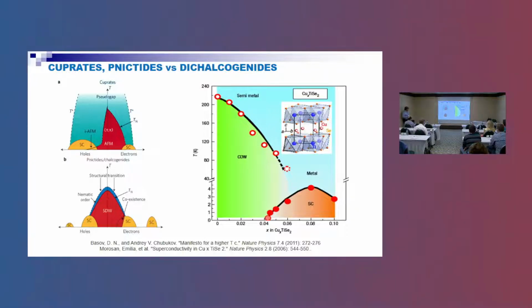Basically, after 30 years of knowing these compounds, people decided to intercalate these materials and see what happens. What is the similarity in all these cuprates and iron-based superconductors? The parent compounds are magnetic. Then if we dope or apply pressure, this magnetism goes away and we have room for superconductivity. Exactly the same we have for the charge density wave, which appears in titanium diselenide. If we intercalate with copper, the charge density wave goes away and we have superconductivity.